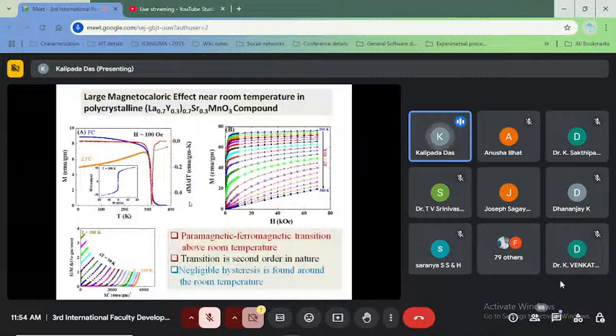Another sample is for room temperature application. For this purpose, we have selected a sample such that its ordering temperature is around room temperature. That's why we have selected yttrium doped lanthanum strontium manganite, because lanthanum strontium manganite is a very well-known ferromagnetic sample, but its ordering temperature is high, about 360 Kelvin. To reduce the ordering temperature slightly and bring it close to room temperature, we have optimized it, and we see that lanthanum yttrium strontium manganite with this composition has an ordering temperature of nearly 300 Kelvin.